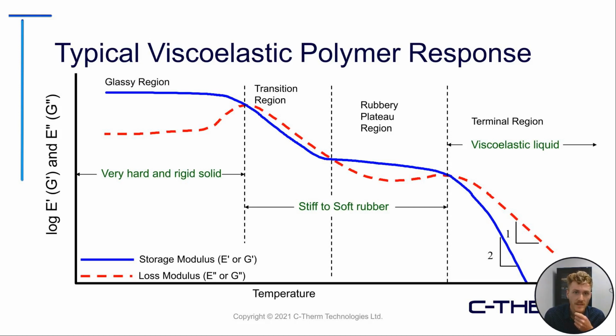As we heat up the sample, we have a transition region, which is dominated by the glass transition temperature and also dominated by the loss modulus as well, spiking. After that, and we heat up the sample a bit more, we reach a region which is called the rubbery plateau, which is heavily dominated again by the storage modulus itself, followed by a terminal region, which is the complete loss of the storage and loss modulus and creation of a viscoelastic liquid.